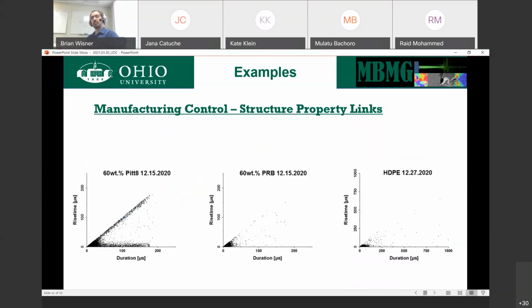Short answer is if we look at the acoustic emission trends for pure polymer versus the composite materials, you'll notice that there are similarities, but large differences. All of them have these burst signals, low duration and rise time, but this material has significantly more activity. So the question becomes, why is that? What is causing this to send so much energy as it's failing that these others don't have?